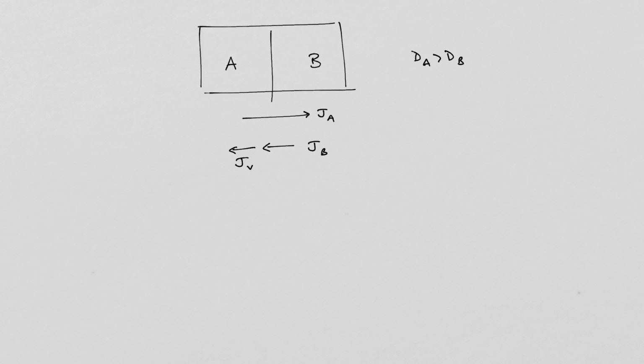Okay, we're getting to two things. One is, well, does the sample move? Because then that would violate all sorts of things, wouldn't it? The centre of mass of that moves, and you started out in the zero momentum frame, and now the thing suddenly seems to have some finite momentum. That can't be right. So there must be something wrong with this picture. Otherwise you'd be able to, for example, put the sample on a slight slope, heat it up, and with the random motion of the heat, you might be able to get the sample to creep up the slope, and then we've got some energy that you could extract, and then, hey, we've broken all sorts of rules of thermodynamics, haven't we? So we need to think carefully about that.